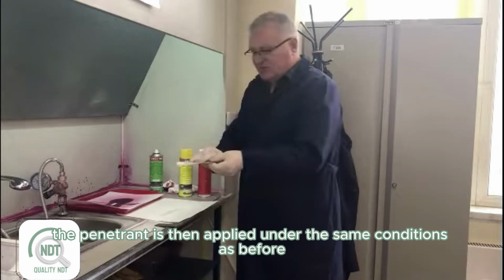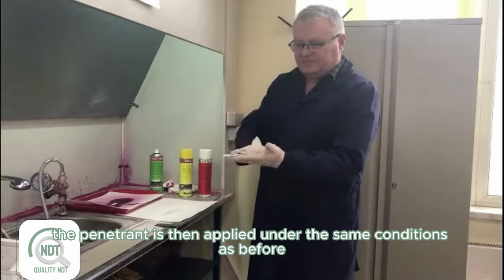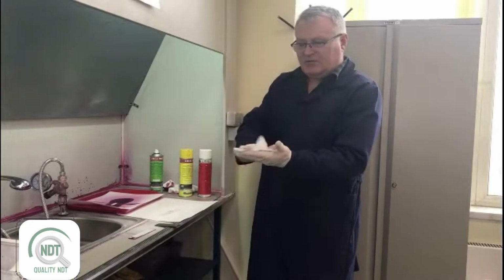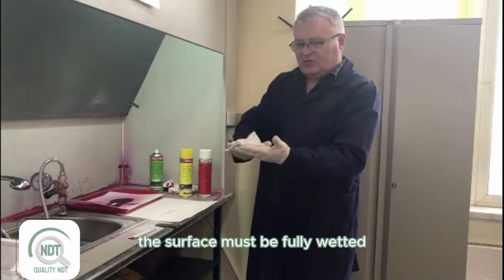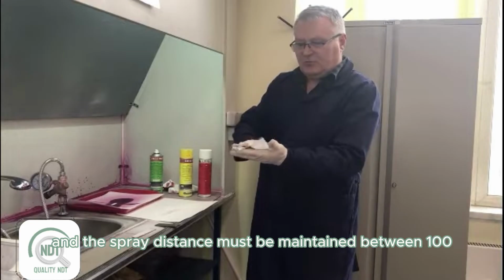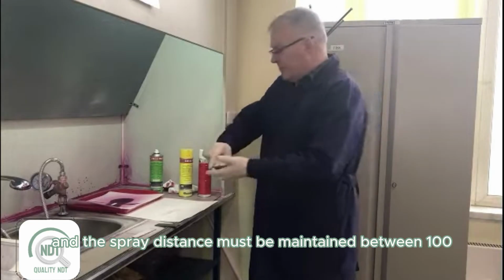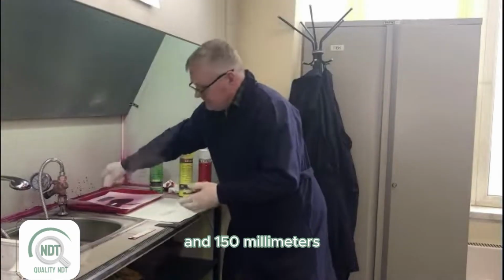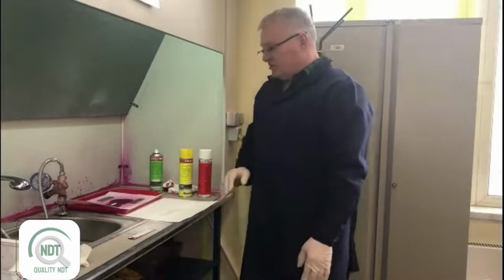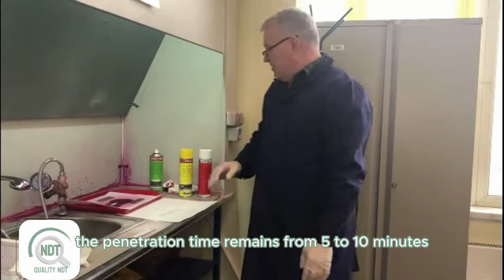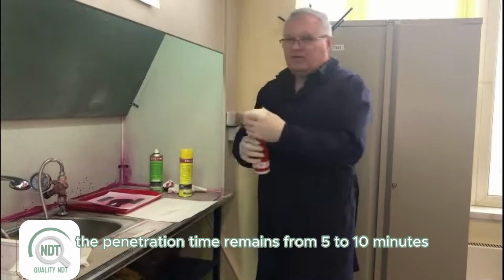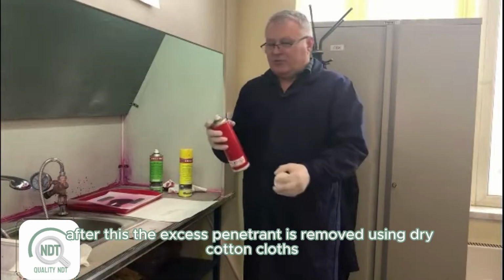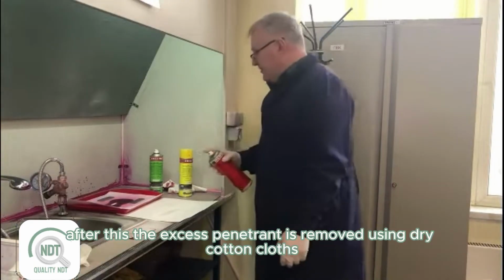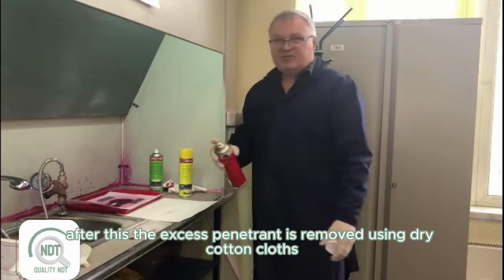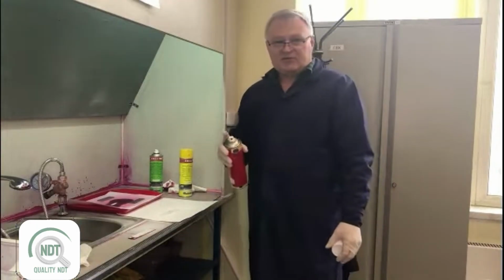The penetrant is then applied under the same conditions as before. The surface must be fully wetted, and the spray distance must be maintained between 100 and 150 millimeters. The penetration time remains from 5 to 10 minutes. After this, the excess penetrant is removed using dry cotton cloths.